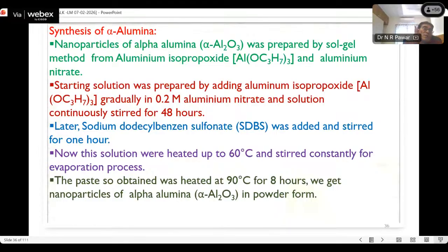And synthesis of alpha alumina. Basically this is also synthesized by the sol-gel technique. Nanoparticles of alpha alumina are prepared by the sol-gel method from aluminum isopropoxide and aluminum nitrate. The starting solution was prepared by adding aluminum isopropoxide gradually to 0.2 mole aluminum nitrate, and the solution was continuously stirred for 48 hours. Later sodium dodecylbenzenesulfonate, that is SDBS, was added and stirred for 1 hour. Now this solution was heated up to 60 degrees and stirred constantly for the evaporation process. The paste obtained was heated at 90 degrees Celsius for 8 hours, and then we get the nanoparticles in powder form.